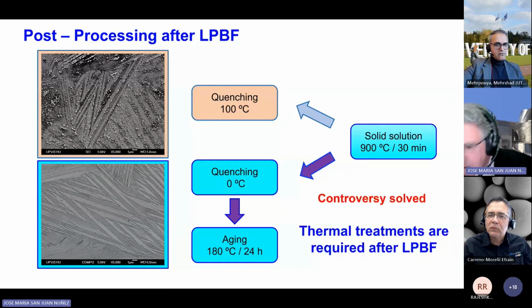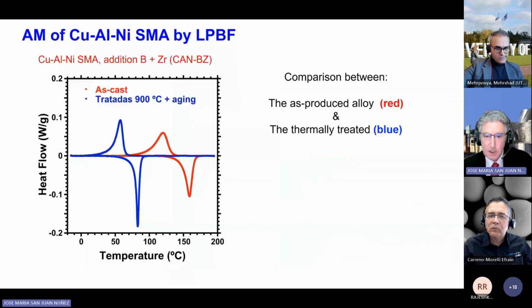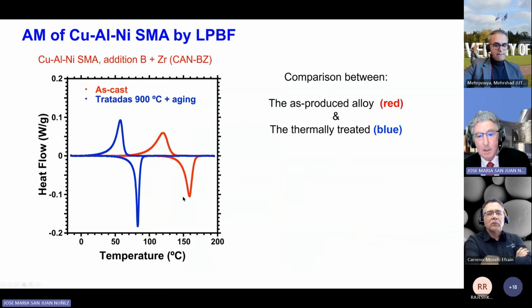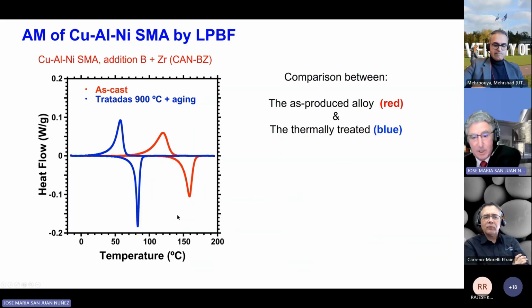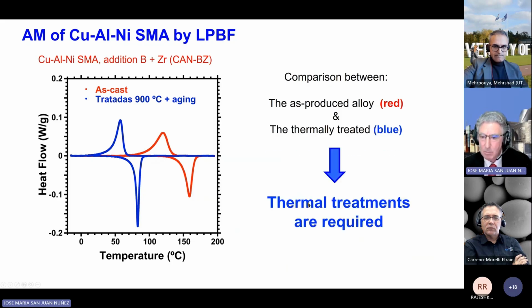So we can say that the controversy is solved. Thermal treatments are required after laser powder bed fusion. This is also seen in the thermograms. Here you can see the differential scanning calorimetry thermograms of the as-cast material that showed all the temperatures fully shifted to high temperature because of the precipitation, and after the thermal treatments, the material exhibits a very sharp transformation at the expected temperatures because of the concentration. So definitely thermal treatments are required, and this is no question.